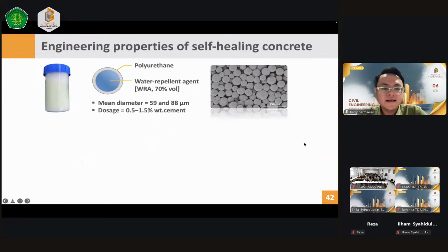Okay. Next, I'm going to discuss a bit about the effect of the microcapsules, which is one of the types of healing agents that we can use for the production of self-healing concrete. So at the time, together with my colleagues from Cambridge, we developed microcapsules with a shell of polyurethane and a cargo of water repellent agent. The mean diameter of these capsules was between 59 and 88 micrometers, with a dosage between 0.5 up to 1.5% by weight of the cement. And this is the picture of the microcapsules inside this slurry or liquid.